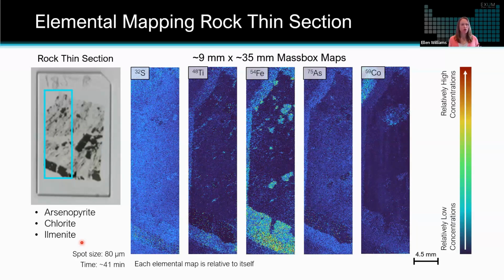So a typical workflow for LA-ICP TOF-MS is to analyze these broad scale, millimeter scale elemental maps with a relatively large spot size. You can see that we chose an 80 micron spot size in this case that allowed us to acquire this analytical area in about 41 minutes.